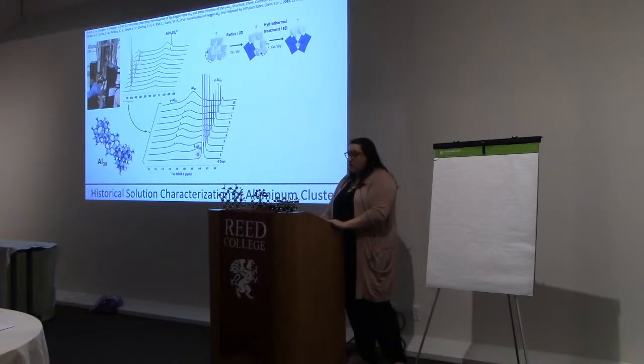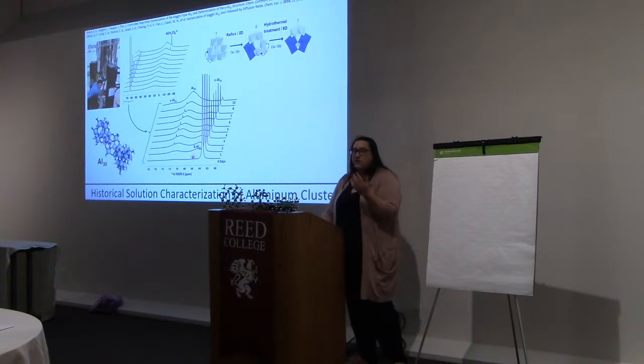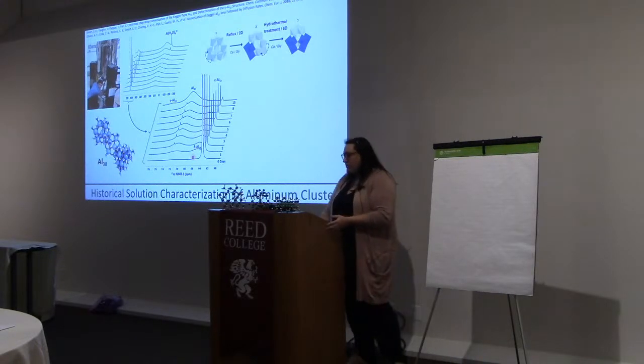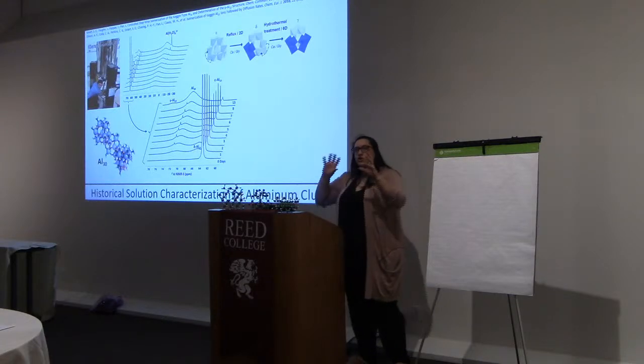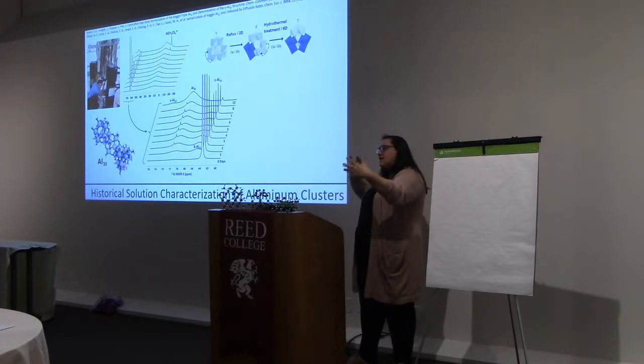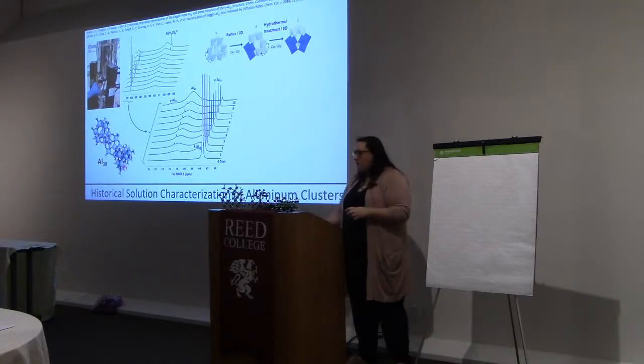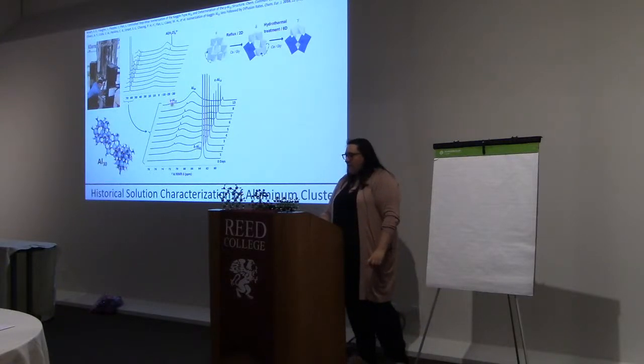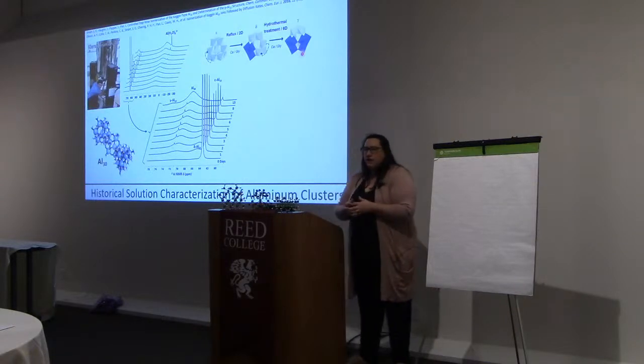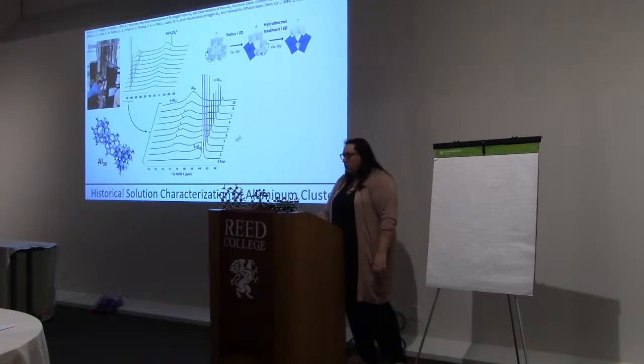After one day technically, our delta starts to grow in, which has already been assigned in the literature to this chemical shift. Then we have this very large signal that grows in here. That's another cluster, the aluminum 30, which is 2 of our delta isomers stuck together by 4 extra aluminums in the middle. And then we have our gamma that started to form here after 2 weeks, which is what was predicted by previous literature. And so we were able to watch that.